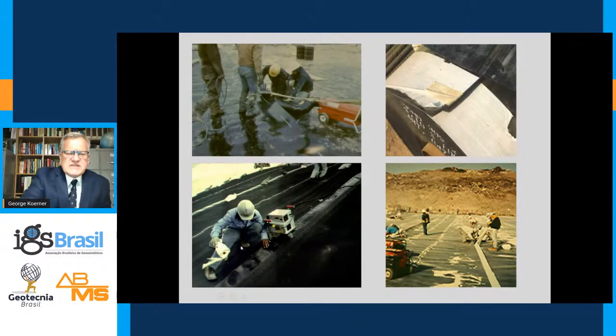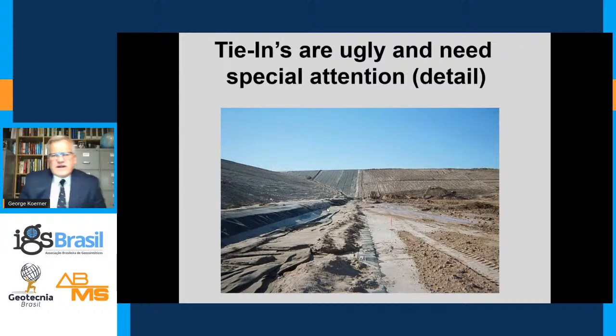Most of the membranes which we see, even textured membranes, have a smooth edge, and this is good for seam quality. Tie-in seams are quite ugly. This issue of tying in one cell to another, this is an active cell which is filled. This is a cell that's being prepared next door to receive waste. The berm separates this, and now to tie in these old geosynthetics to one another is problematic. You sometimes see a lot of elaborate protection systems. It can be with plywood or other geosynthetics which are pulled up in advance of the seaming, but certainly should be thought about with great care.